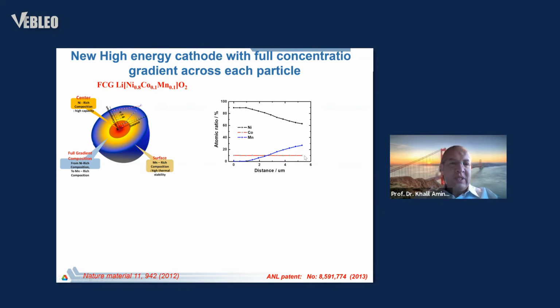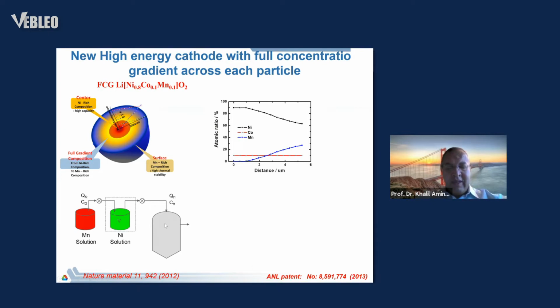The first question is, is this material scalable? The answer is yes. We use a co-precipitation. The conventional NMC that is used in electric vehicles uses only one tank that has a defined concentration of nickel, manganese, cobalt, and you send it to the reactor, and you have a chelating agent and co-precipitating agent, and you form your material. Here we have two tanks, one that is nickel rich, the other one is manganese rich. We start sending nickel to form a nickel rich bulk, and then we dilute the nickel tank with manganese, and we slowly change the concentration by growing the particle.